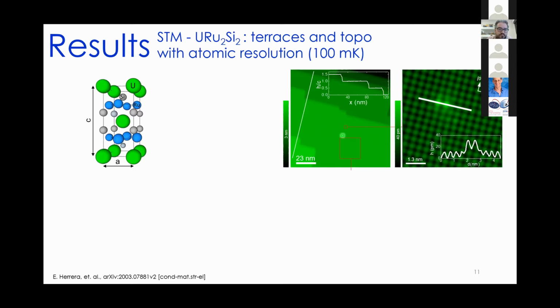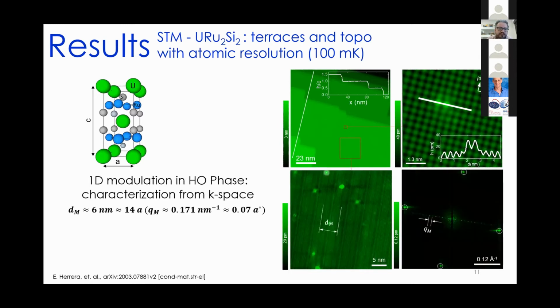In larger fields of view, with fewer steps and defects, we observe a certain pattern which repeats on the image here, and you follow here the pointer, and it's one-dimensional. Okay, here in the Fourier transform, we can observe the usual Bragg peaks for the square atomic lattice, but here at the center, we observe multiple peaks, with a distance that we call Q sub m, which is the evidence of this 1D modulation. The period of the modulation in real space is 6 nanometers, and it corresponds to this value in the reciprocal space.